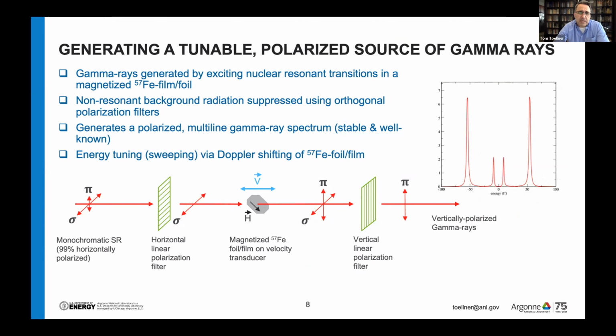So here we take a magnetized iron foil placed between cross-polarization filters, and it's arranged in such a way that we excite all 6 resonances. The net result is you get a combination of sigma and pi polarized radiation that is resonant in between the polarization filters. All the sigma components are suppressed at the pi polarization filter, and you just get the resonant pi radiation out. So the output beam of this instrument will be a pi polarized 4-line spectrum, as you see there.